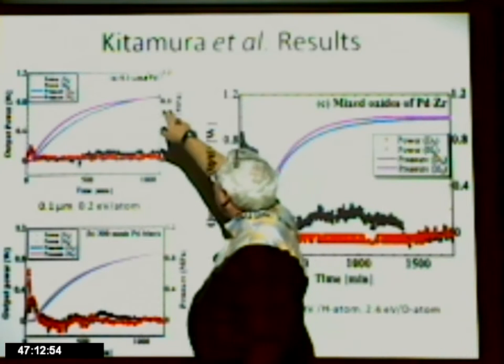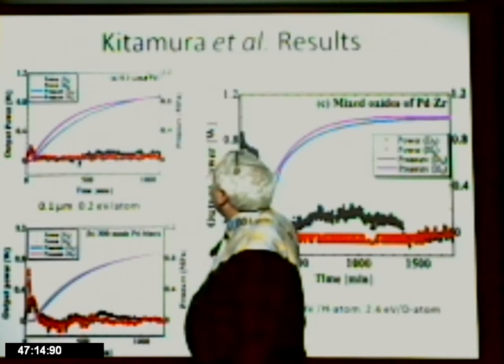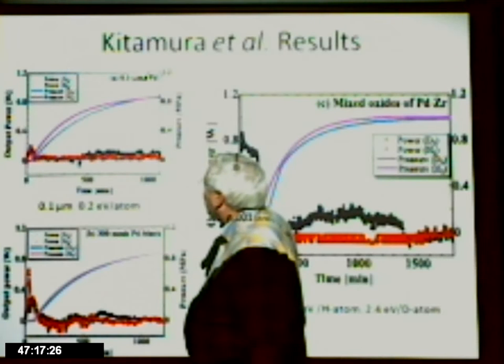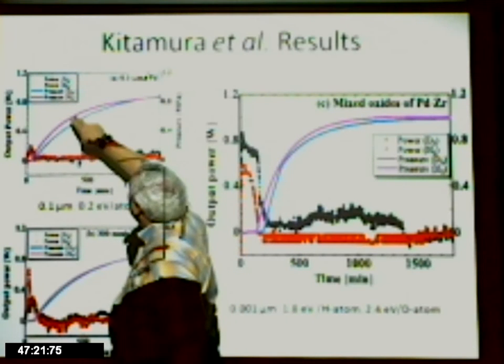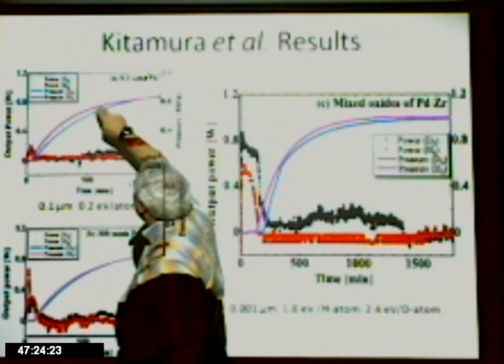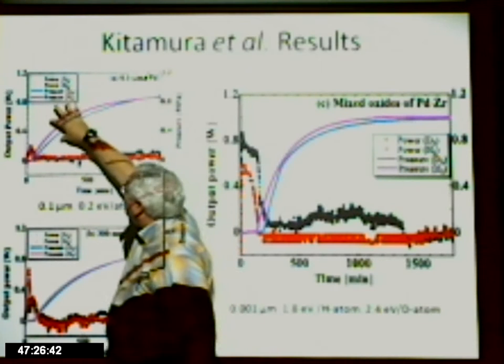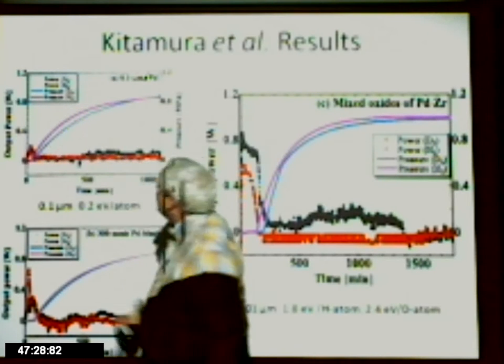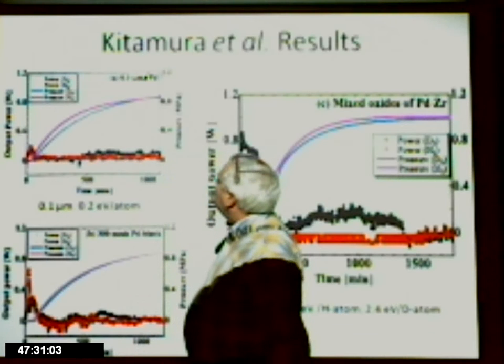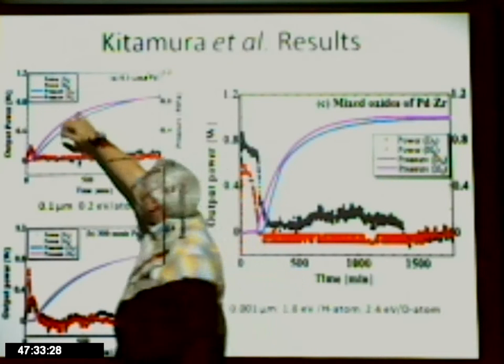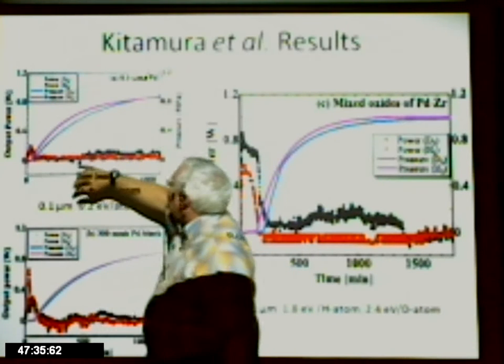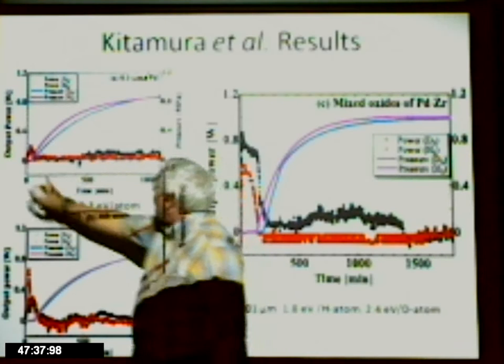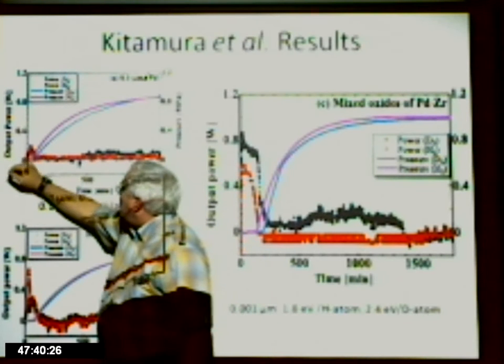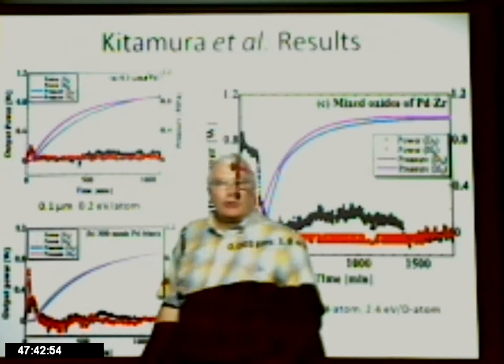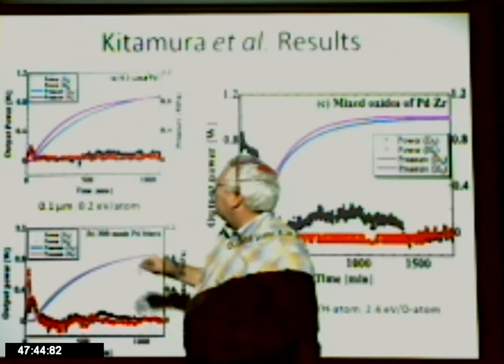First, he starts with palladium black, which is about 0.1 micrometer, 10 to the minus 7 meter diameter palladium spheres on average. And what's shown here is the pressure of D2 in blue and the pressure of H2 in purple. Again, this isn't the same sample. There's one sample being used for D2, another sample being used for H2. And then what he's showing is the excess power seen from H2 and from the D2 experiments. Both show this blip, and this blip is what would be expected due to the surface heat of absorption of the hydrogen onto the palladium metal.